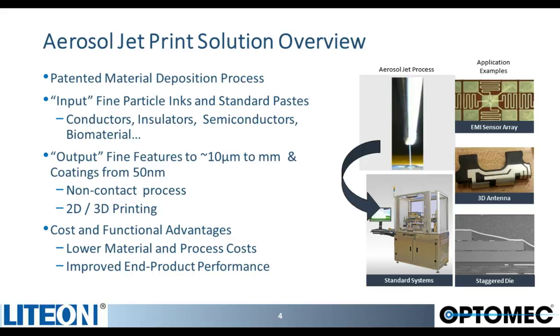And from that input of materials, we then output very small droplets that enable us to print fine features as small as 10 microns to millimeters in scale, so we can scale up and down depending upon the process parameters we use. And we can do coatings from 50 nanometers on up, depending upon what the customer's requirements are. So thicknesses typically range in the 500 nanometers up to 8 microns in a single pass with our materials.